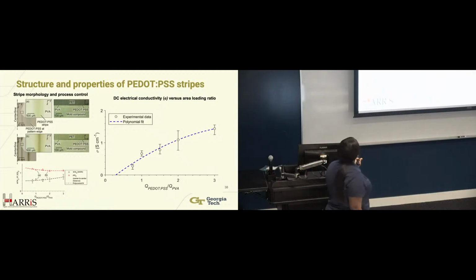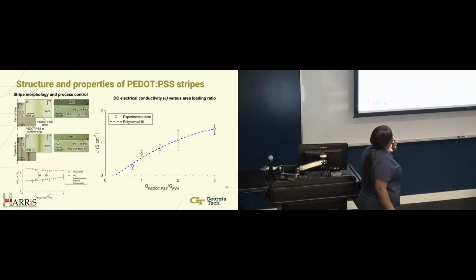So here's functional, PEDOT:PSS. And as you can see here, this is about 500 microns for those who are in the back. We have PVA as the, we'll say, scaffold material. And while you get a little bit of spreading and mixing at the interface, you have a distinct line here. And then here, it's a little bit more spread out and more flat, not as concentrated, but it is still distinct. And so we felt strongly that, okay, we can process this material. Depending upon the processing conditions, we'll get a little variation in terms of the density of the fluid in the core region.